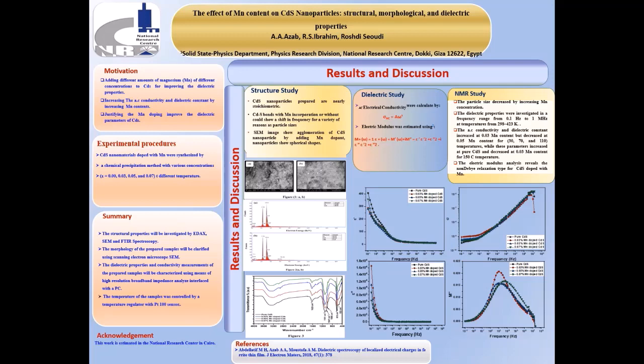and study the structural properties and the dielectric properties to use in several applications such as digital recording media. From figures, we can confirm the structure of cadmium sulfide by EDX technique and find that cadmium sulfide is nearly stoichiometric. And also we can study the Fourier transform infrared spectra and confirm that cadmium sulfide is formed.